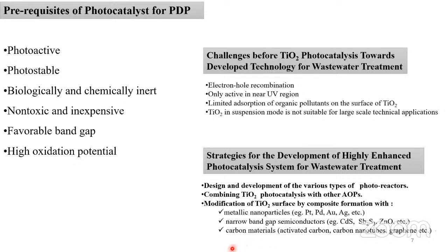And next is the modification of TiO2 by carbon materials, or preparing composites with carbon materials like activated carbon, carbon nanotubes, graphene. One of the advantages, as they are carbon materials, is that the surface area is increased. So there is increased adsorption of organic pollutants on the surface, and they also act as a good electron sink. So that is another advantage of it.